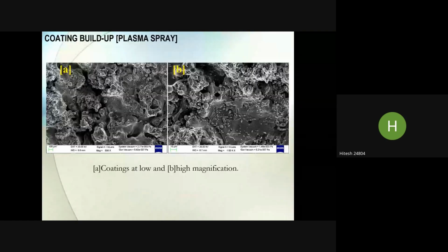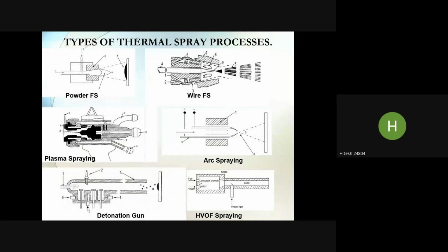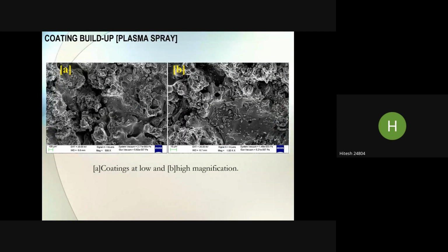unmelted. But in this process, you can see that it is a plasma spray, as I mentioned in the previous slide. Plasma spray technique is used for the deposition of materials with high melting point. So on this surface there are very few unmelted particles because we have increased the temperature range. If the melting point is high, then obviously we have to increase the temperature accordingly so that we can get fewer deficiencies on the surface or in the material.